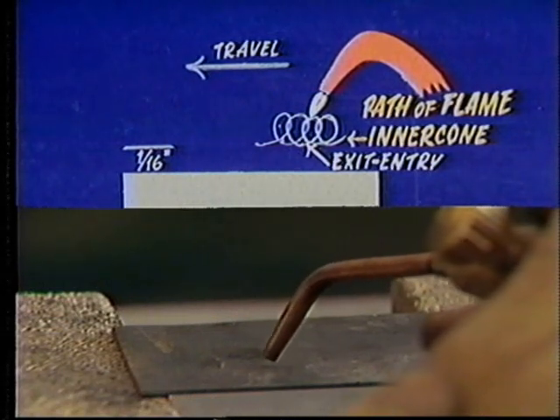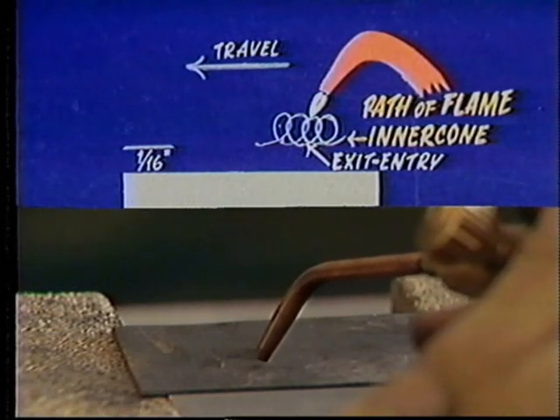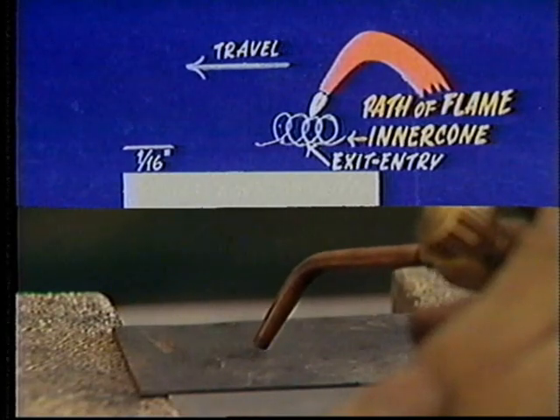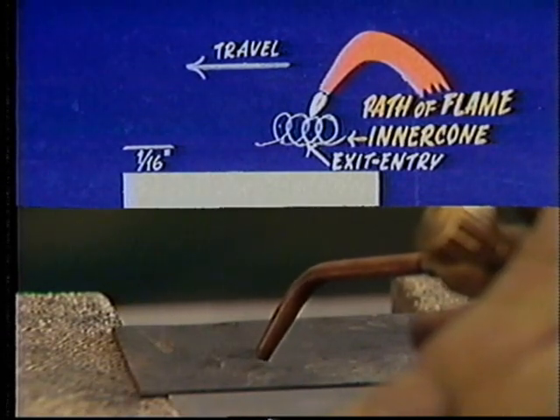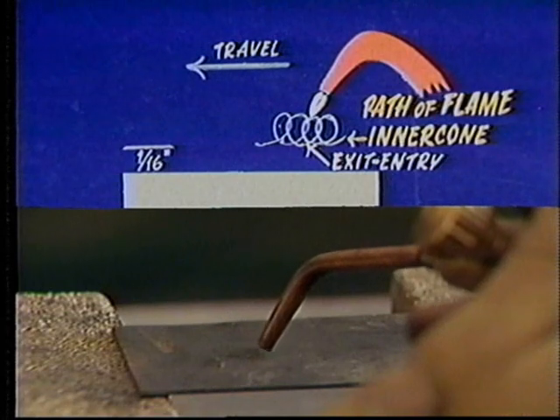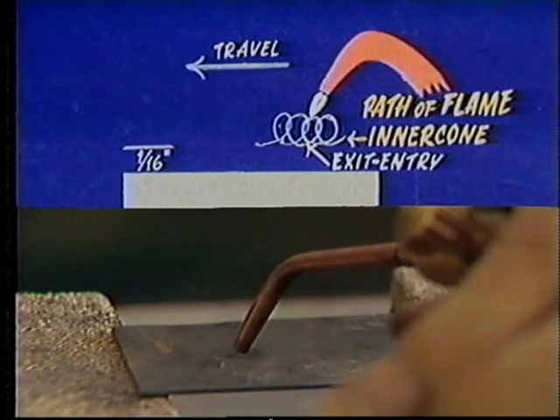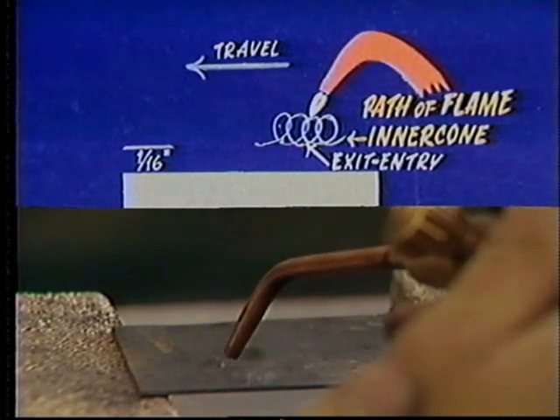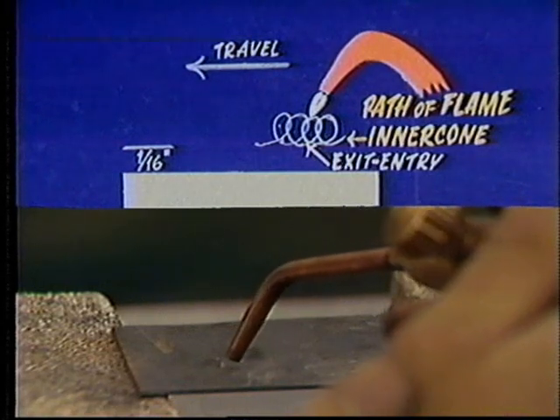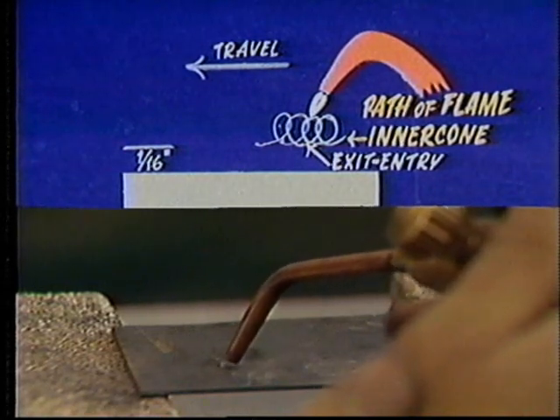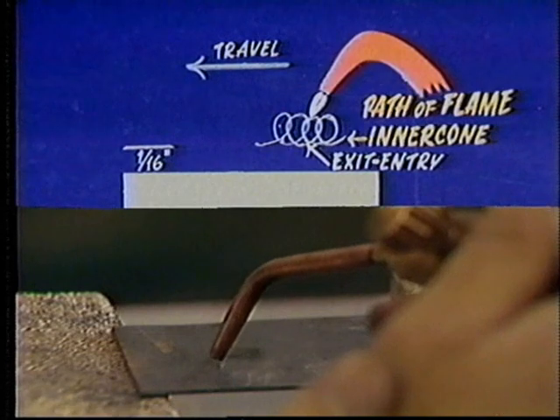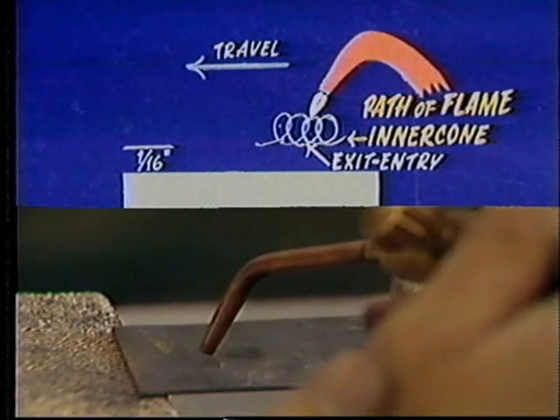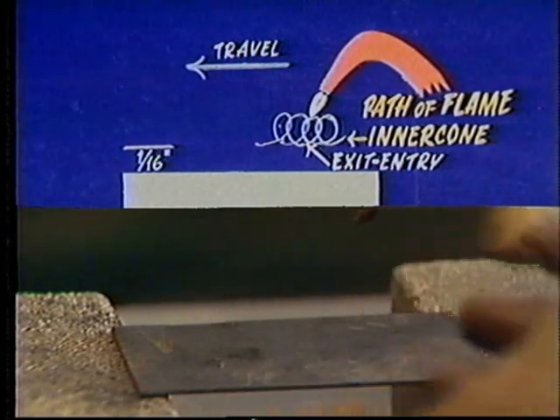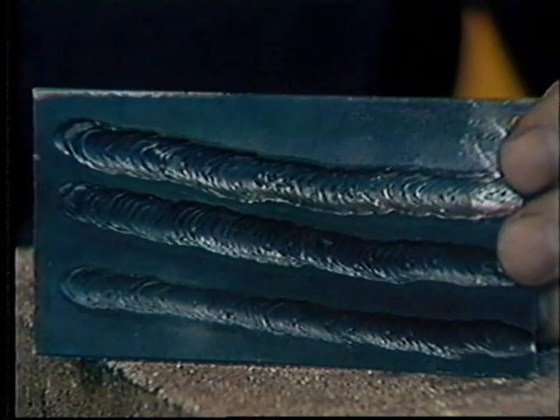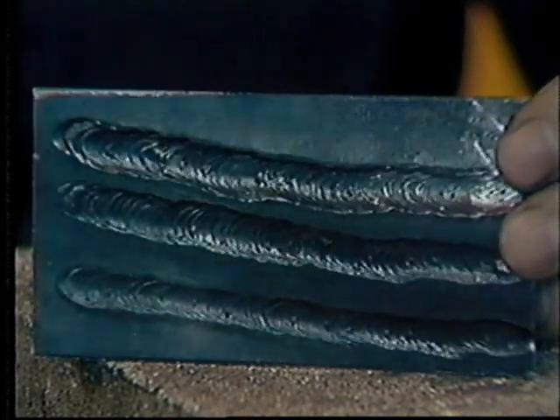And is the height critical? Yes, it is. He should never bring the inner cone closer than about 1/16, and usually not more than about 3/8 of an inch away from the base metal at any time. What would happen if the height was too high or too low? If he moves it too far away, the puddle cools too much. If he moves it too close, he can introduce impurities.